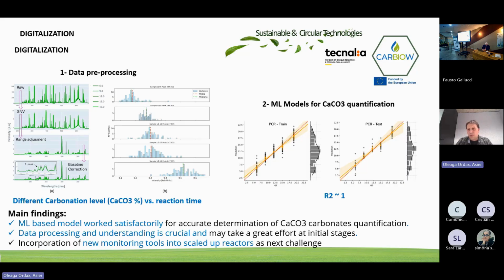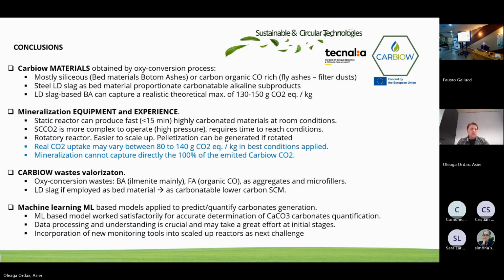And also to work not only on the new carbonation quantification, but also to understand which type of properties are changing, which is the reflection on properties such as material grading for cements. So that's all. In conclusion, of the materials in this project, only LD slag was carbonatable. We get close to the maximum, which is about 150 grams CO2 per kilogram. Of course, depending on the equipment and the carbonation protocol, you can get more or less capture. You can increase the temperature or pressure, but you are complexifying too, and the industry normally doesn't accept too complex and costly processes, of course.